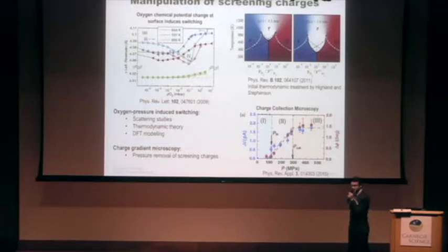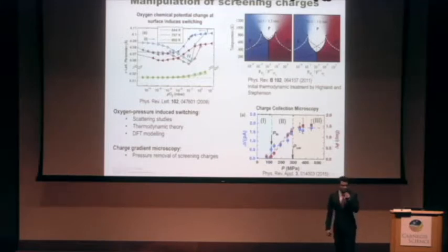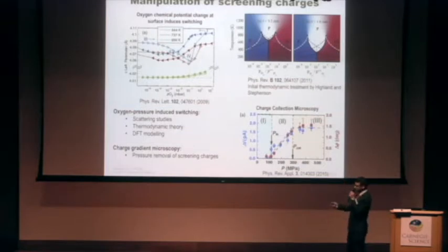You see this nice butterfly hysteresis. So without applying any electric fields, they're able to switch their polarization. So this obviously has something to do with screening on the surface. They did some calculations, the initial thermodynamic treatment, and what they found was that for this particular thickness of lead titanate, there are different states of polarization that are preferred under different partial pressures of oxygen. So this is exactly what they saw in experiment.